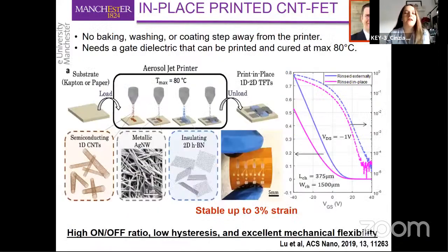So in the first example, we basically collaborated with Aaron Franklin at Duke University, and he's an expert on printed transistors made with semiconducting carbon nanotubes. And we implemented our boron nitride inks into the device fabrication. And basically, Aaron was able to demonstrate that it's possible to produce a high-performance device by fabricating the device completely under the inkjet printer. So typically, the device will need to be annealed or washed and so on. All these processes are being made by using the capabilities of the inkjet printer.